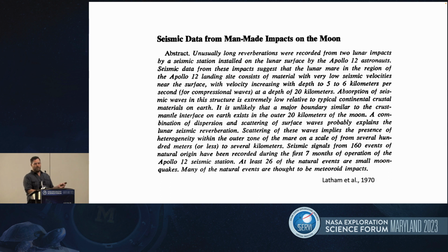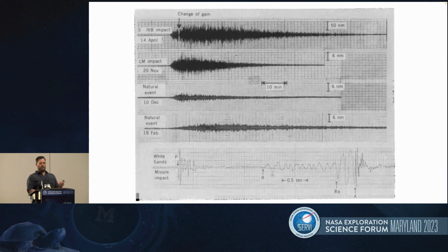So a long time ago, during the Apollo missions, they were noticing an extremely interesting seismic signal, which was that there seemed to be very low seismic absorption in the lunar regolith. Here are some seismograms of some impact experiments, and you can see that the seismograms ring out for tens of minutes. Basically, this pile of rocks was ringing like a bell. And as a comparison, here is an impact test from White Sands, New Mexico, at relatively similar energy densities, but the signal basically dies out in a matter of seconds.